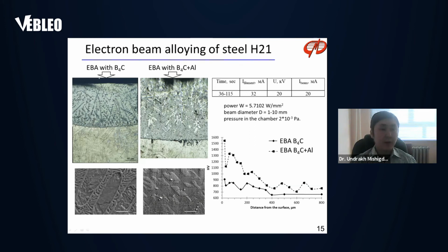After a single boron carbide alloying, we see a lot of dendrites placed in a light matrix, and the magnified picture showed its cellular structure. After two-component alloying, we see that rhombic crystals form. These are probably iron borides, and they contribute to enhanced microhardness, as we can see here. Microhardness after two-component alloying is much higher than after single-component electron beam alloying.